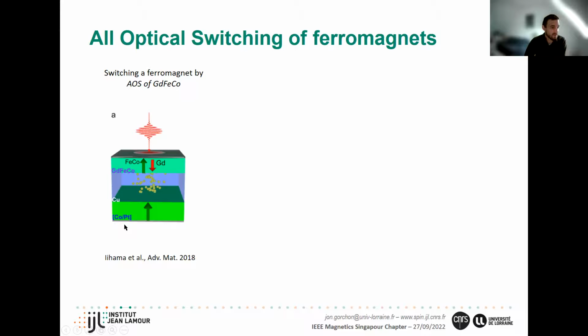And we can select if we switch one or the two, depending on the fluence. So we can actually reach 4 different states of magnetization by selecting the fluence of the laser. And what we demonstrated in this work is that the actual spin current that is driving the switching of the cobalt platinum is the spin current that's parallelly aligned with the gadolinium spins. So it's rather the spins from the gadolinium than the ones from the iron cobalt, which was a bit surprising